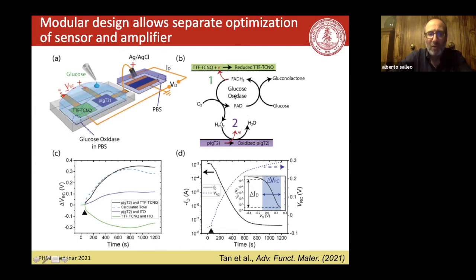So when you have glucose that gets oxidized and you have this cofactor, the glucose gets oxidized and it generates hydrogen peroxide. Well, the hydrogen peroxide is an oxidant, and so it can steal an electron from this electrode in the reaction cell. So it can oxidize this. So this increases the potential of this.